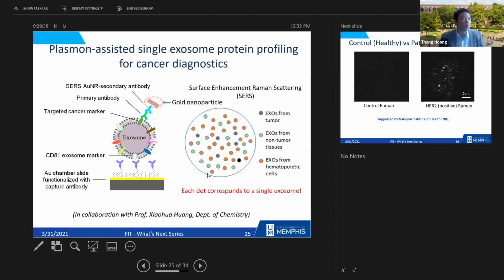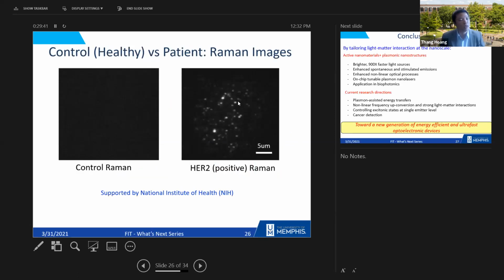We demonstrated that. For example, in this case, I show what we call the surface enhanced Raman image, right? Each of these dots you see on the right is from an exosome from a patient that has cancer, stage 4. And on the left, you see a Raman image from an exosome from a patient who is healthy. So you can see a clear difference in the Raman signal from the two different patients. This research has been supported by NIH to allow us to detect cancer at a very early stage.